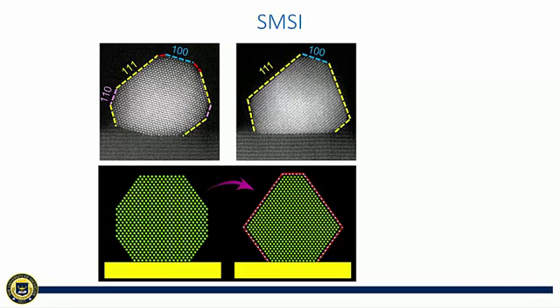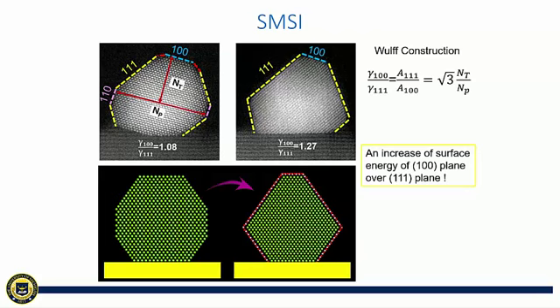So I labeled each facet. Here the top surface is the 100 facet. The bigger ones on both sides highlighted in yellow are 111 facets, and the two smaller ones highlighted in purple are 110 facets. If we compare the initial stage with the final stage, we can clearly see the disappearance of the 110 facet, the expansion of 111, and shrinking of 100.